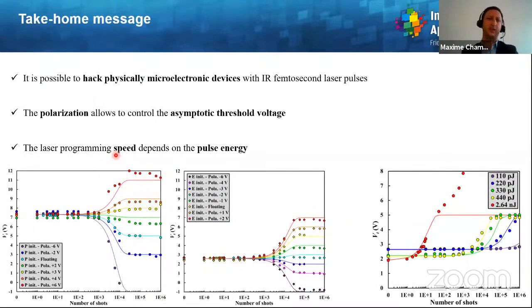So here is the take-home message for this part. It is possible to hack physically microelectronic devices with infrared laser pulses. The polarization allows us to control the asymptotic threshold voltage, and the laser programming speed depends on the pulse energy.